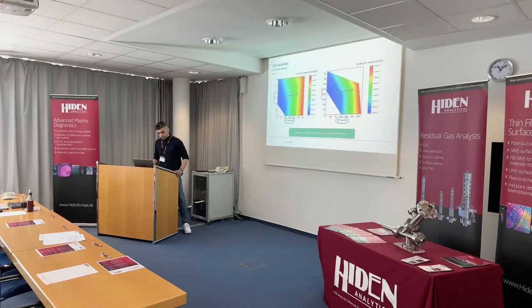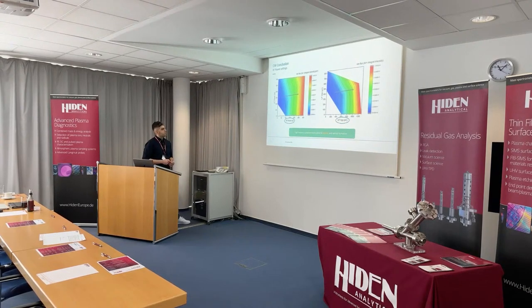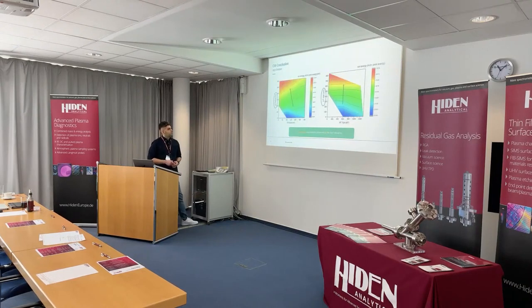And this is the conclusion for continuous wave. You see the HF power and LF power influence on ion flux. So ion flux is mostly influenced by HF power, and you see the HF VPP, which is the product of HF power, and it only corresponds to higher frequency. And the lower frequency is what gives higher ion energies. So when the LF power is increasing, the ion energy is increasing. And you see this effect better in LF VPP.